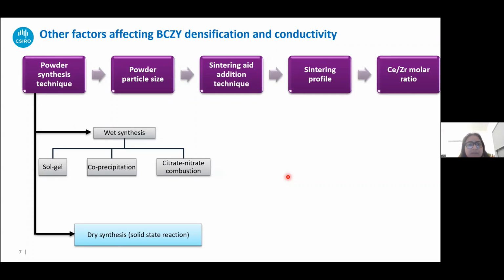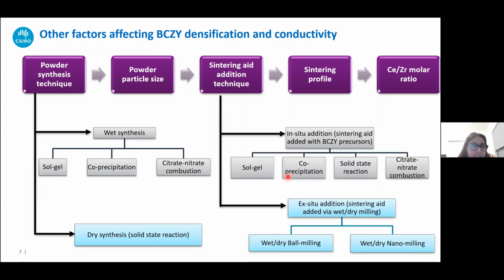Now, the next thing that affects the BCZY densification is obviously the powder particle size, then also the sintering aid addition technique. So here there are two pathways again. One is the in situ addition, where the phase evolution of the BCZY takes place while the sintering aid is already present. So the sintering aid is added at the very first step, where we are preparing the liquid solution with the precursors of BCZY.